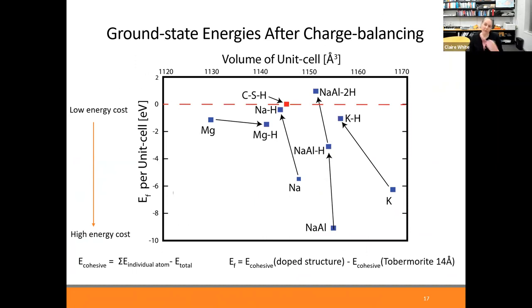So just to recap, what we found is essentially a charge balancing mechanism whereby if you replace a calcium atom with a sodium atom, if we have a hydrogen atom that's in the vicinity as well, that's added, then we end up with a stable structure that's comparable to the initial tobermorite crystal structure. Now, you might say, okay, why a hydrogen? Why not another atom? And we also tried one calcium for two sodiums. That's not as energetically favorable. So we found that the hydrogen atom, probably because of its size, is favorable to have, whereas if you're looking at, say, two sodium, they take up too much room, and that's causing some of the issues when it comes to the overall energy of the system.